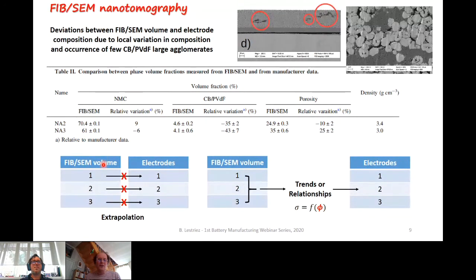So because we have a discrepancy between the volume composition of the FIB-SEM volumes and the corresponding electrode, all that we observed on the FIB-SEM volumes cannot be directly extrapolated to the corresponding electrodes. But because we have studied different FIB-SEM volumes, we were able to establish trends or relationships, for example, the dependence of a property on a given phase volume fraction. And then we have used these trends or relationships to better understand the electrodes, but this time taking into consideration the true volume fraction in the electrode.